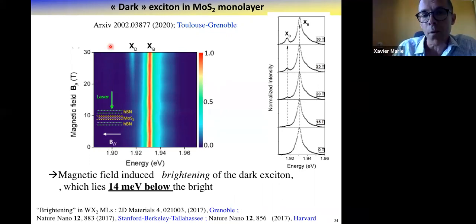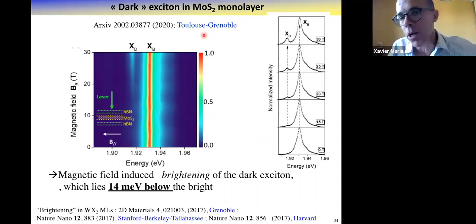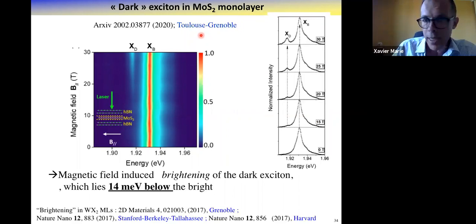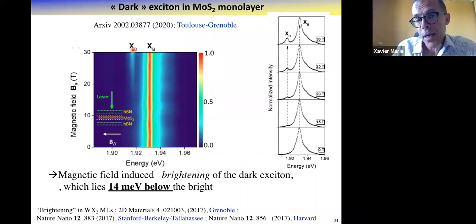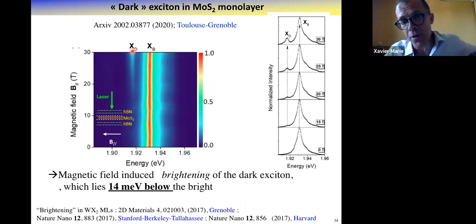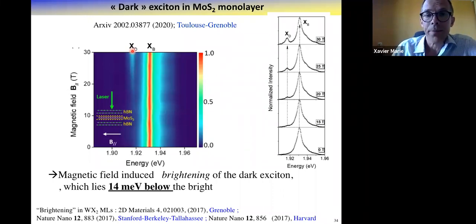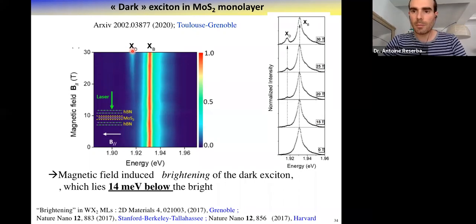There are different reasons. One of them, in contrast to WSe2 and WS2, if you look at the energy difference here, 14 millielectron volts, it's smaller than the LO phonon energy in MoS2. Whereas in WSe2, it's larger. So the relaxation to the dark exciton maybe is weaker, and this is why you have trouble to populate it. Another reason is the spin mixing. Molybdenum-based monolayers have lower spin-orbit interaction. So the spin mixing, which is a key ingredient to observe a gray exciton, is probably weaker than in W-based material.